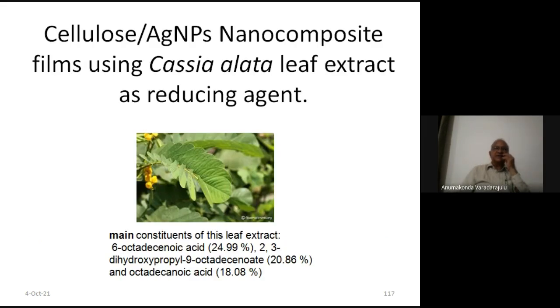Then we use another leaf extract, Cassia alata leaf extract. This leaf is known as Tangedu, which is very famously used in Bathukamma festival. In another 2 days, Bathukamma festival starts in Telangana, which is a unique festival. And this particular leaf has got many biochemicals, and it has got many medical applications also. So we used its leaf extract as a bio-reducing agent because it has got several biochemicals, which can reduce the metal salts into their metal nanoparticles inside the matrix, in situ generation. We are not generating outside, but we are generating inside the matrix itself.